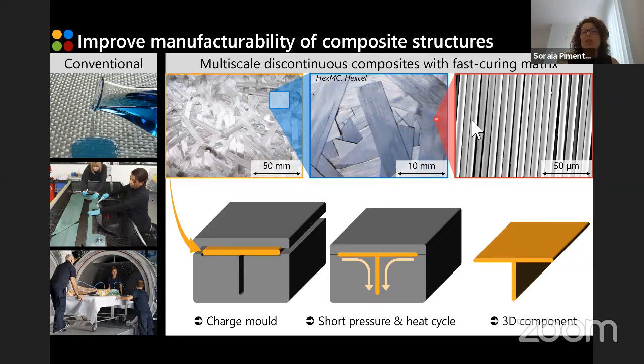Now, the fact that we have these two scales means that on the one side, we can pack the fibers very efficiently inside the composites, and on the other side, we have a discontinuous and randomly oriented structure, meaning that we can just take a charge of the material, put it inside a mold, apply heat and pressure, typically with short cycles because we are using fast curing matrices, and off we have our 3D component in a much faster and much cheaper way compared to if we were following a conventional process as highlighted on the left-hand side.